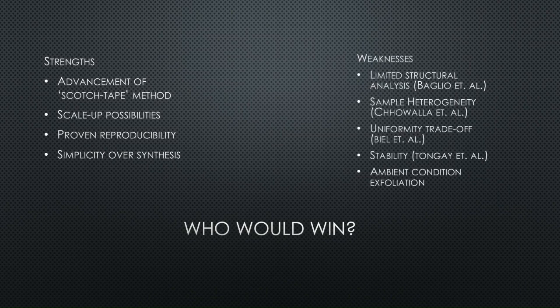So, what are some of the weaknesses? Well, although XPS information about the chemical composition was very robust, the study could have benefited from additional techniques such as Raman as a complementary method to provide more insight into flake thickness and lateral dimensions, and possible defects that the XPS could not capture. Another example would be the paper mentions reproducibility of XPS spectra, but would be stronger with a more in depth statistical analysis that quantifies the variation across multiple numbers of samples.